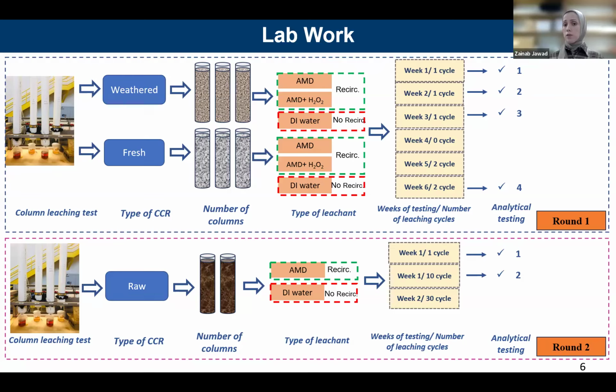We did the testing for 6 weeks. During the first 3 weeks, we did one leaching cycle per week, and then we collected a sample by the end of the cycle and sent it to the lab for testing. We stopped for 1 week for data processing, and then we decided to go with multiple leaching cycles after that. So we did 2 leaching cycles during weeks 5 and 6, and by the end of those cycles, we collected a sample and sent it for testing.